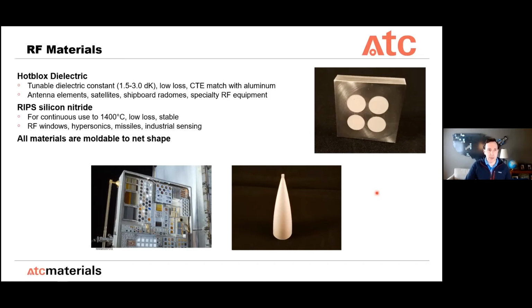The other material, and this is where I've spent most of the time today, is our material which we call RIPS. It's a silicon nitride version, and that's for elevated temperatures, where hot blocks is good to 350 or 400 degrees C for short use. RIPS is a silicon nitride, so it's stable to 1400 degrees. And this is what's caught the interest of the hypersonics community and allows us to manufacture the windows for the sensors and seekers on these vehicles that experience significant aerothermal heating and other extreme environmental effects during their Mach 5 or greater flight.